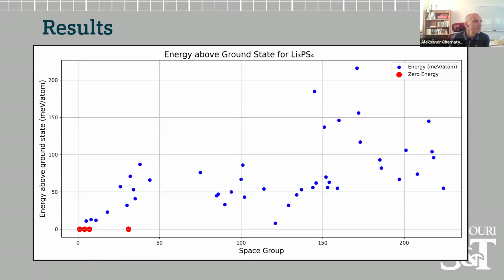In this particular system, the lowest energy, so-called gamma phase of Li3PS4, crystallizes in group 31. And you can see that I also have 3 other groups where I found the same structure. These 3 other groups are group P1, which is of course a subgroup of every group, and the other 2 are group number 4 and group number 7, both of which are subgroups of 31. So this idea that I can find a given lowest energy structure in every subgroup of a given group allows me a consistency check, and it gives me some degree of confidence that I have found what I wanted to find.